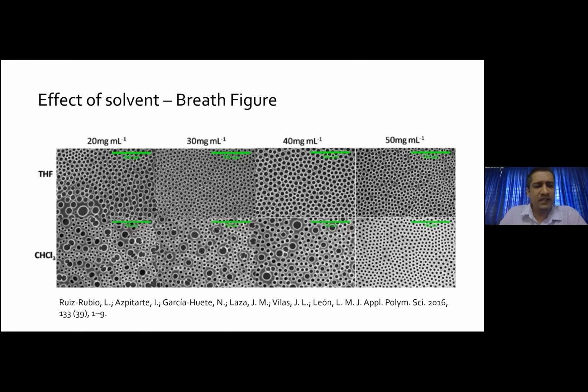When the same experiment is carried out at a very high humidity of 90%, as observed earlier, chloroform gives multimodal pore formation, whereas THF showed a more or less even distribution of pores. The inference the authors made was the following: you need to have an optimum flow rate, and the optimum flow rate is a function of the solvent polarity. The optimum flow rate is also a function of the viscosity present in the thin surface.